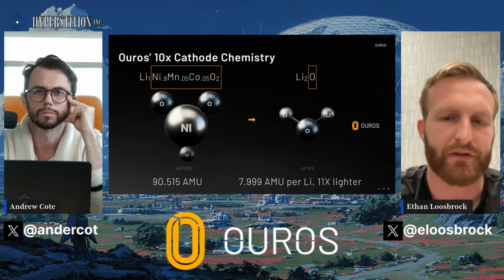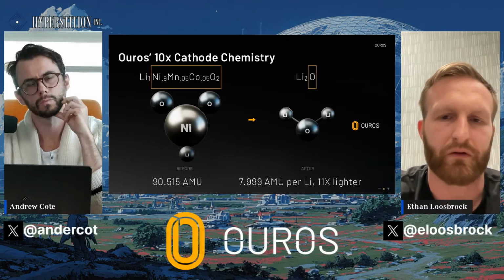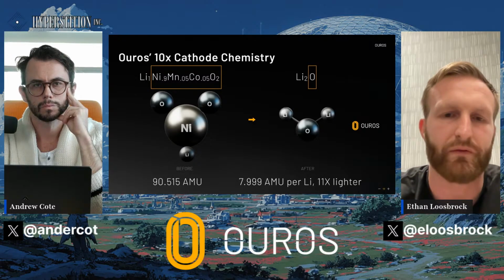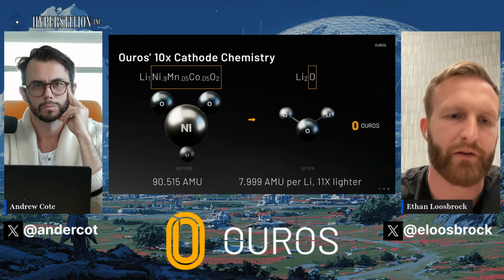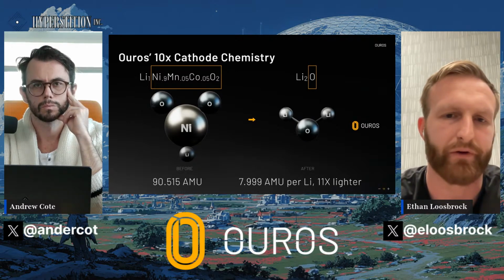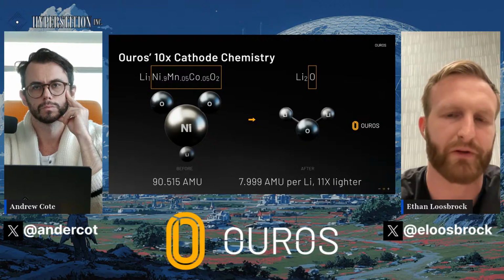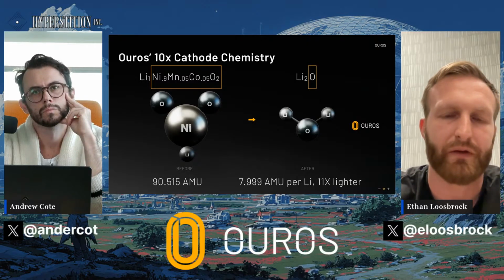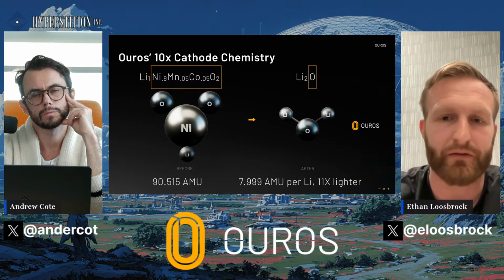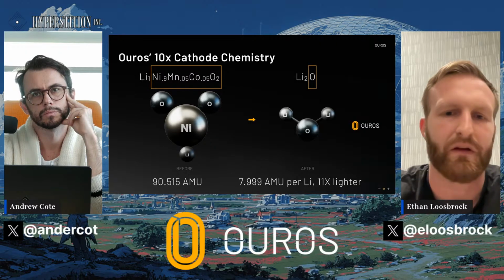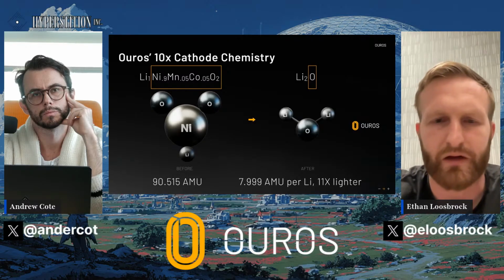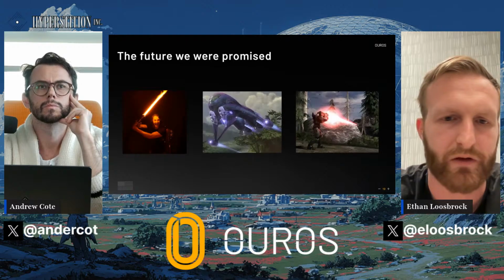And also oxygen can accommodate different valence states. Oxygen can have a -2 charge like it typically does. It can also have a -1 and also a -1/2. And so as long as you don't pull all of the lithium off, it'll stay a solid, and you can use it in a much more reversible way. You also can seal your battery completely to the outside, which is absolutely necessary for any sort of cycle performance. The downside is you now have to carry the mass of the oxygen, so it's not quite as light as it could be. So the numbers are, I have this slide.